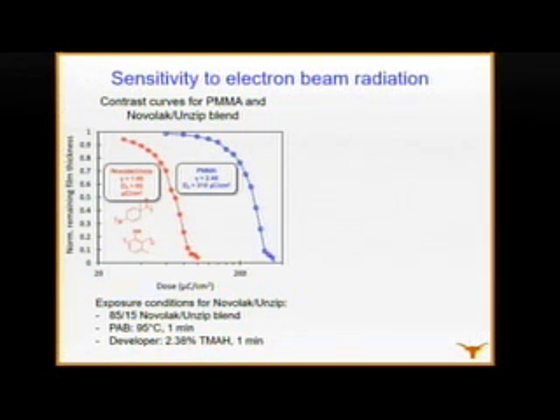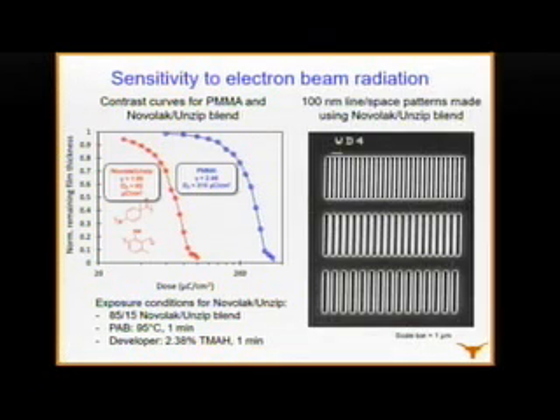Here we're shining differing doses on it and seeing how much of the film is left after exposure. At low doses, it doesn't dissolve at all. At high doses, it all dissolves away. This is polymethyl methacrylate, which is sort of like a standard resist for this kind of exposure. And this is the new stuff. It's obviously a lot more sensitive than PMMA. And it makes nice patterns.